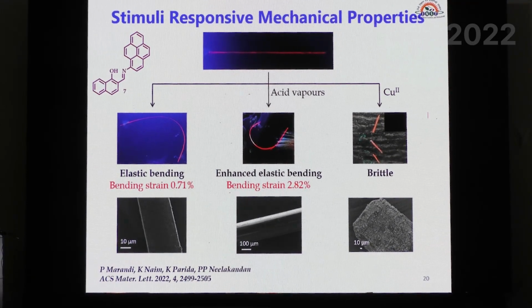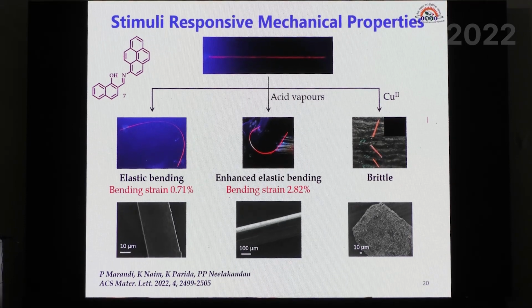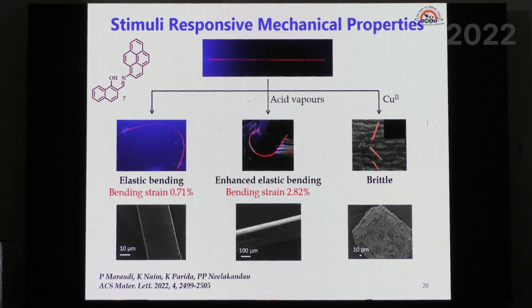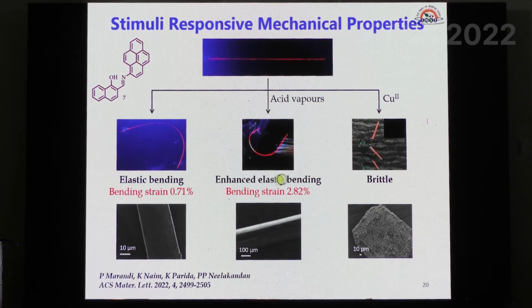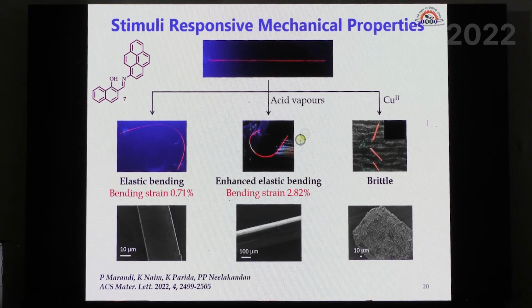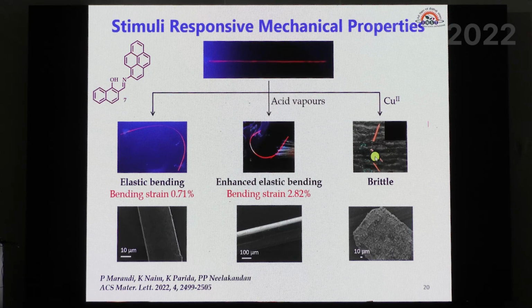But if you treat it with copper, that means we took this crystal and dipped it in a solution containing copper, when you take it out, it loses its flexibility completely. And the fluorescence is also completely gone. In a similar way, when you try to bend it, it simply breaks. I don't have videos, but it simply breaks. I can show the photos.